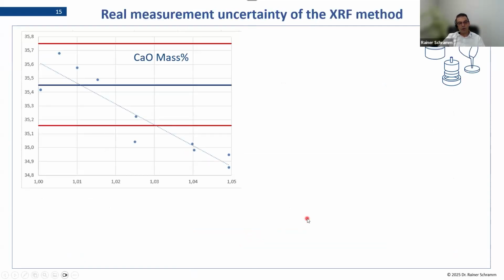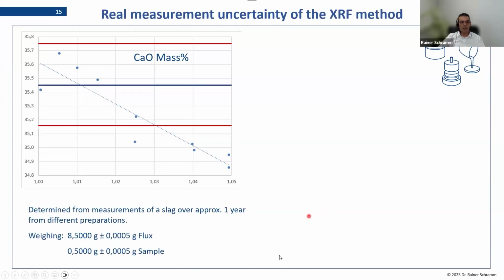Another investigation I did was to check how additives, like an oxidizer in a slag method, affect the final results. So what do you see here? You see a slag sample, which is 0.5 gram, and the flux 8.5, so they were weighed together. And the values for the exact weighing were exactly here for the given value. So this is the given value of my slag sample for calcium oxide, and this is the classical laboratory error we see. So all these weighings are inside the error.